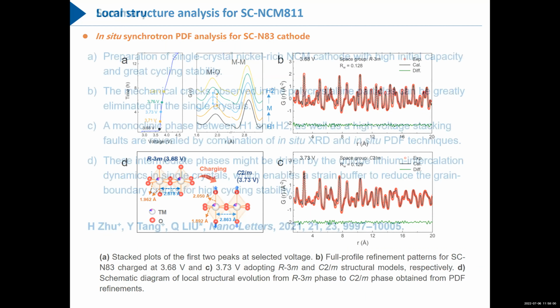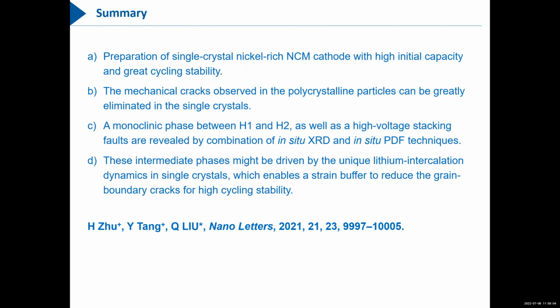Finally, a summary of this part. First, we have prepared single crystal nickel-rich cathode materials with large scale synthesis. We found that the mechanical cracks observed in polycrystalline particles can be greatly alleviated in the single crystals. Importantly, we find a monoclinic phase between H1 and H2, as well as a high voltage stacking. We believe these two phase transitions and the unique lithium intercalation dynamics in the single crystals enable a strain buffer to reduce grain boundary cracks. That's the main reason why single crystals have a much higher capacity retention in these materials.